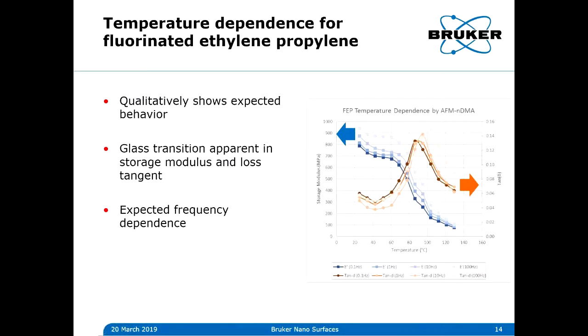So what if we try this with AFM-nDMA? We need a bunch of spectra at different temperatures. So this is doing this on a fluorinated ethylene propylene sample. And we have in blue the storage modulus, and then in orange the loss tangent. We have the spectra. So the spectra are kind of these different colors of blue. And then we have different temperatures, right? So we have temperature on the x-axis here.